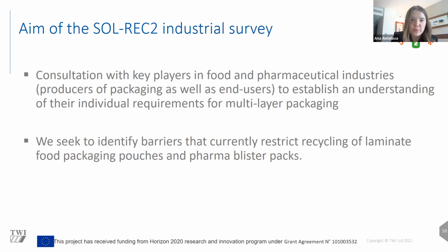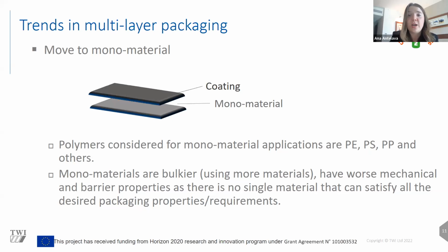So during these discussions, we identified some clear trends that were highlighted to us. One of them is the move away from multi-layers due to challenges with the separation of layers, sorting and collection, as I highlighted, and to move to monomaterial. So industry is considering using polymers such as polyethylene or polypropylene increasingly for monomaterial applications. However, it presents challenges. Monomaterials will be bulkier. They will utilize more virgin materials. They also have worse mechanical and barrier properties. And the reason for this is that there's no single material that can satisfy all your desired packaging requirements and functionalities that you can obtain with composite laminate packaging.